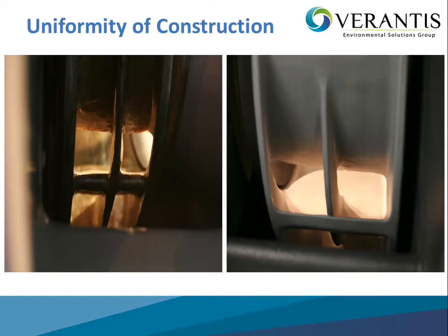Uniformity of construction. Our competitor on the left shows irregular surfaces that can cause uneven buildup of contaminants, increased vibration and instability. It can also compromise the integrity and the strength of the impeller. On the right is our impeller, which stays in balance for longer periods of time and is not subject to the same problems that our competitor has.